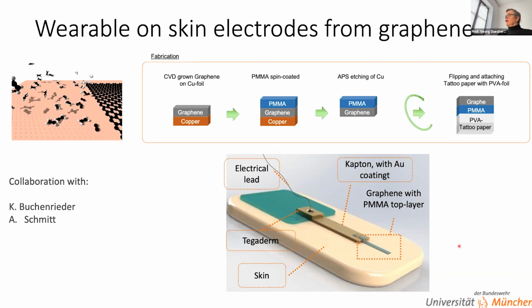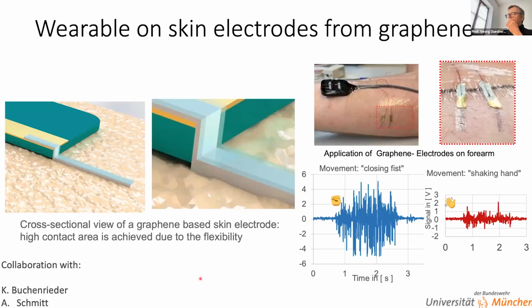Just as a reminder, the competition is metal-based electrodes, which cause skin irritations, or the suction electrodes, or polymer gel-based electrodes, which tend to dry out over time and cause skin irritations. And the idea is that this very thin monolayer plus polymer layer can really have conformal or intimate contact to the skin as shown here. And basically we can attach these tattoos directly onto the skin.